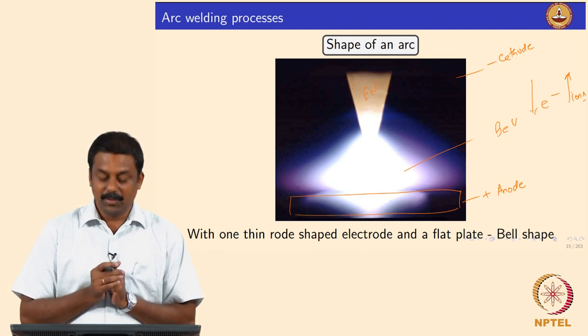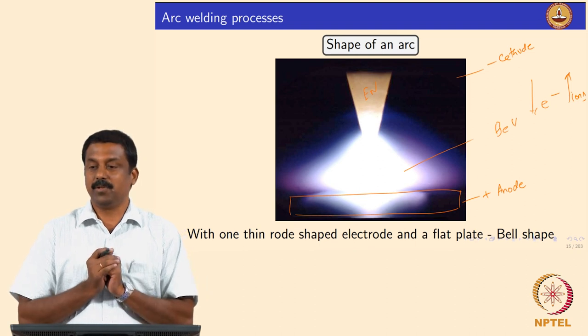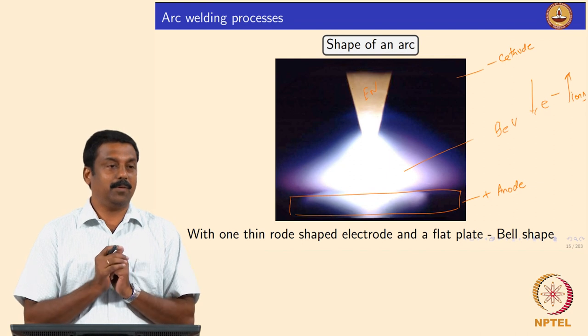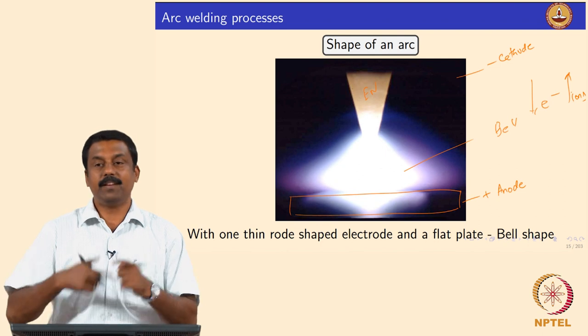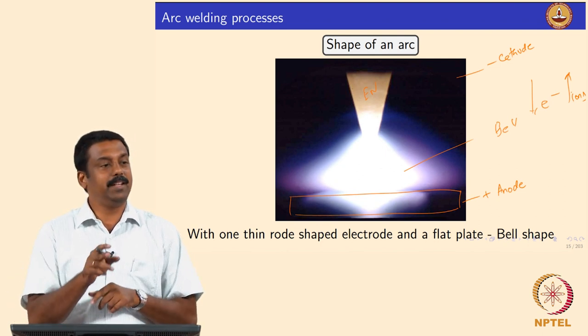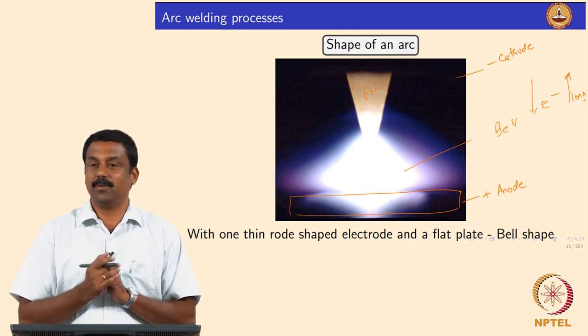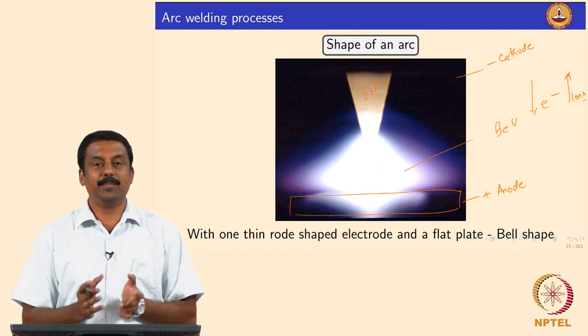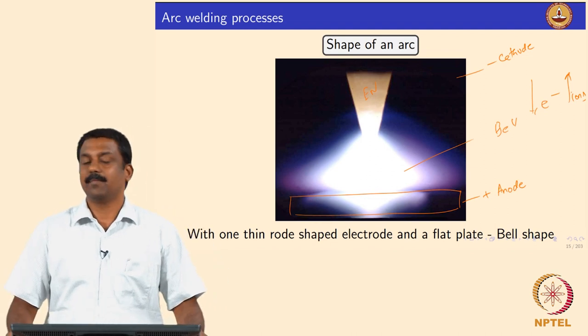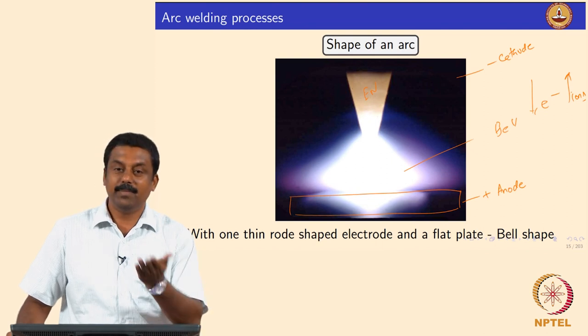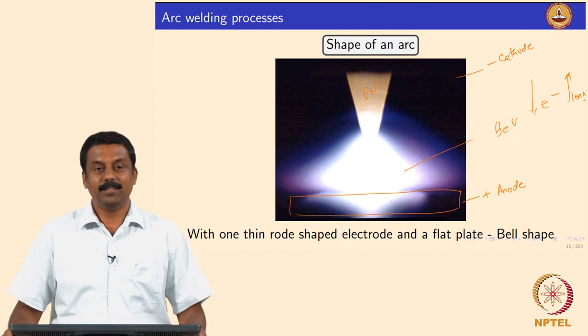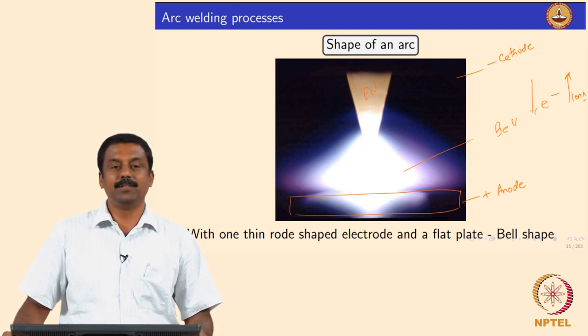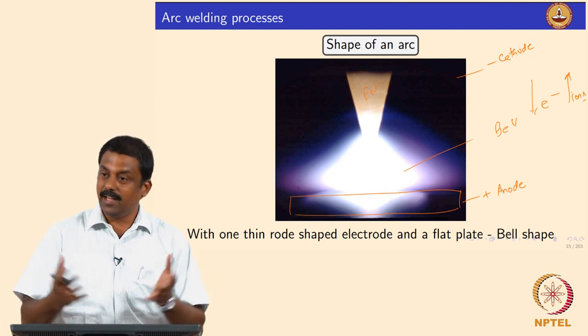When using a non-consumable electrode set to negative, electrons emitted from the electrode are sent to the workpiece, and the workpiece temperature goes high. If you reverse the polarity, electrons will reach the electrode — that is not good for a non-consumable electrode. You will end up damaging and eroding the electrode much faster. Electrode positive (EP) is beneficial if you use a consumable welding process where the filler wire needs to be molten.